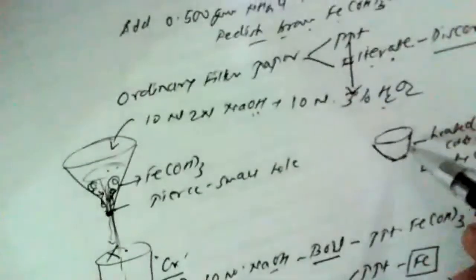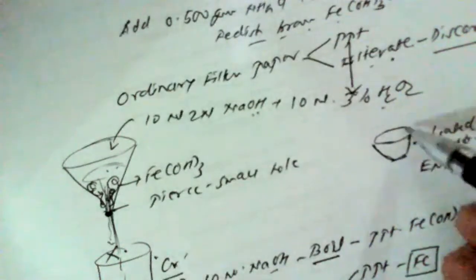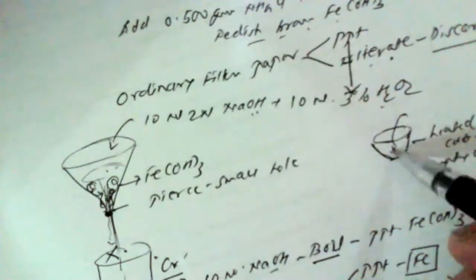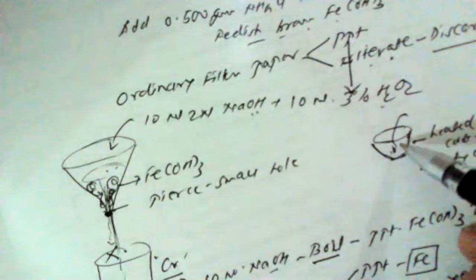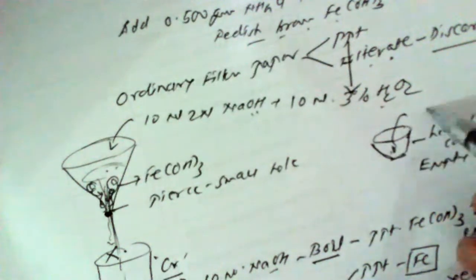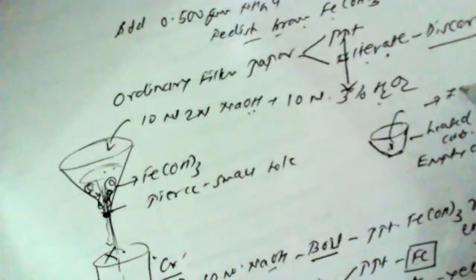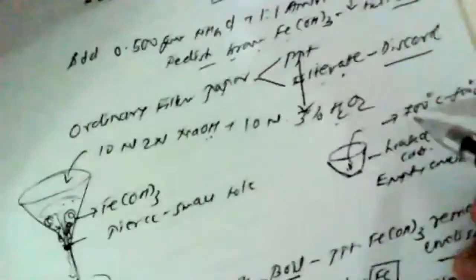This dried precipitate, along with the Whatman filter paper number 41, we have to keep in this crucible, and this crucible is to be heated electrically at around 700 to 800 degrees centigrade.